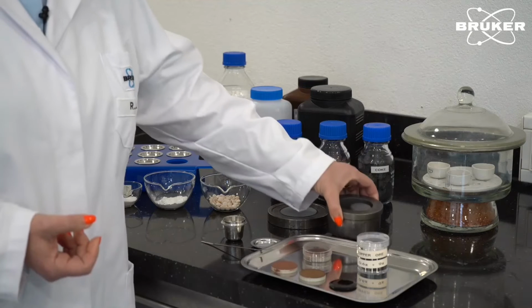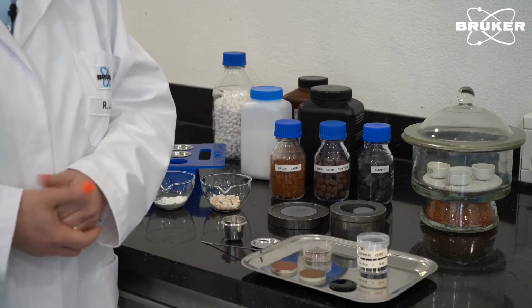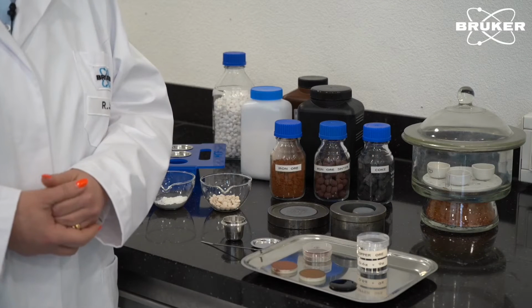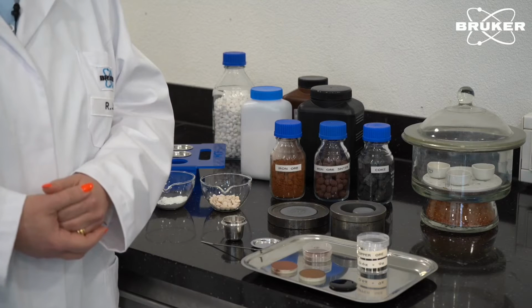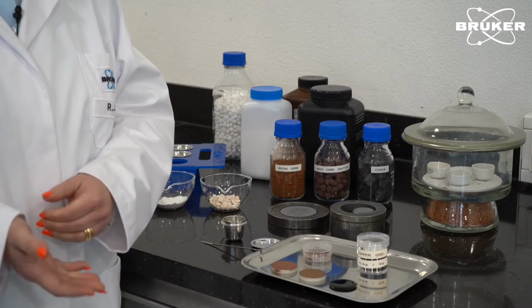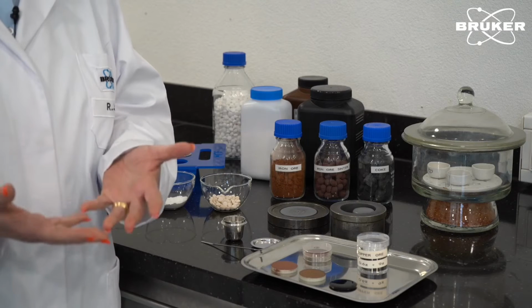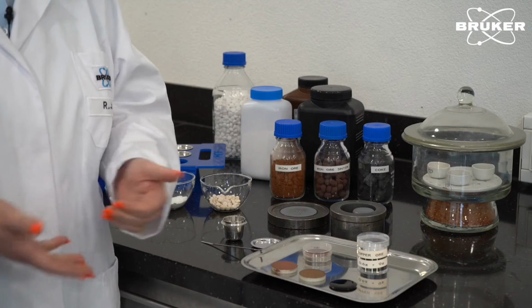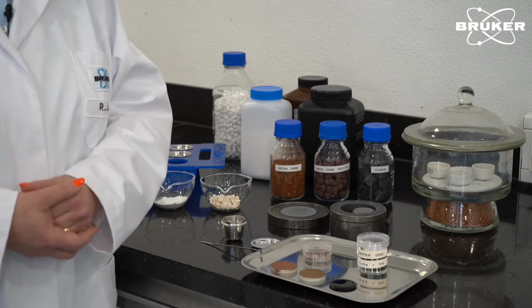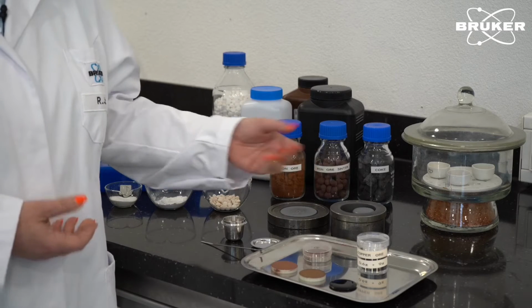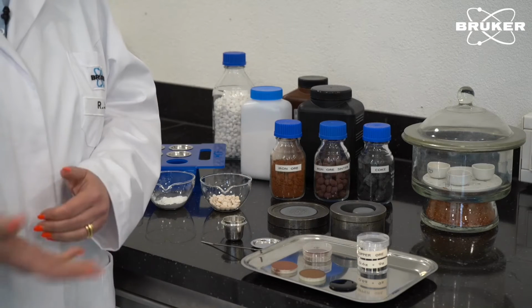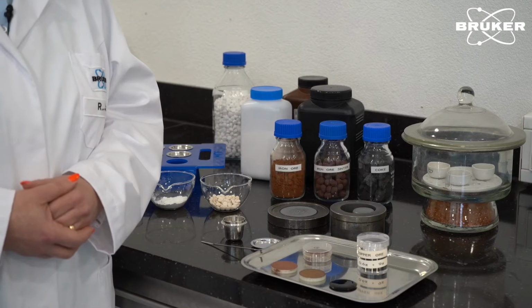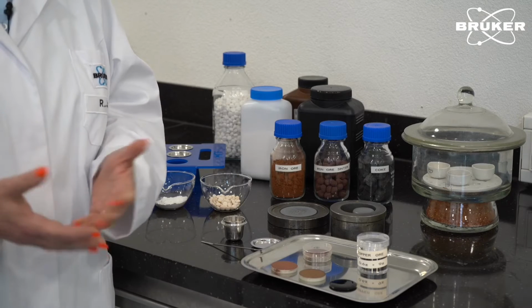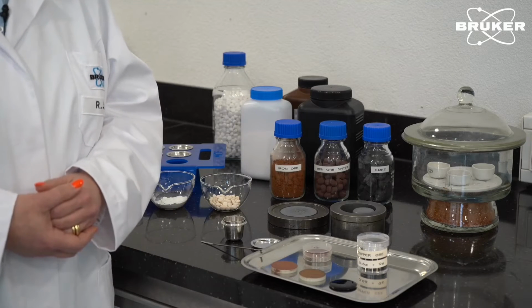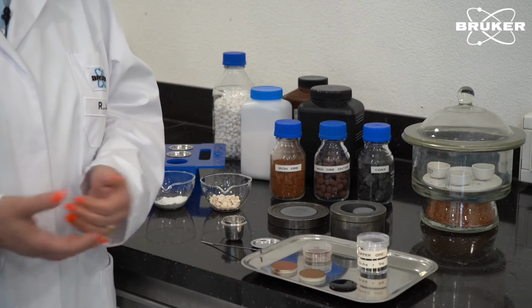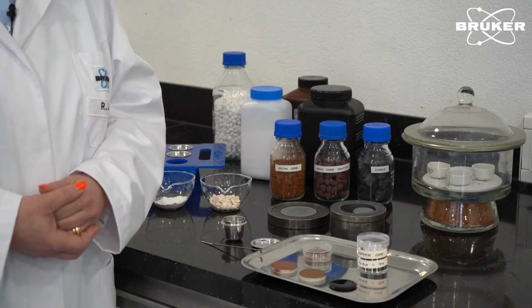The vessels are available in different materials. So I think the most common materials which are used in this area are steel vessels and tungsten carbide vessels. The big advantage of a tungsten carbide vessel is that it's a very hard material, so you can grind more or less all material. What you have to think about is, of course, that for each vessel material, you also have some contamination. So for a steel vessel, you will, of course, have some iron or maybe some chromium as traces, which is contaminating the material. And for tungsten carbide, of course, you will always see some traces of tungsten and also some cobalt.